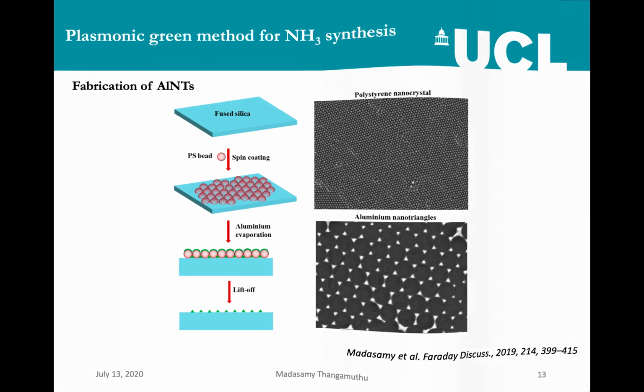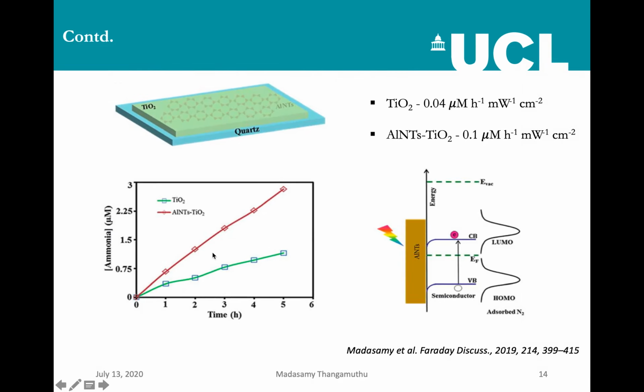In this case, as you can see in this schematic of the electrode, once I fabricated the aluminum nanotriangles, I deposited about 100 nanometers of titanium dioxide semiconductor on top of it. So in my case, who is generating the charge carriers, or where is the electron to reduce the nitrogen molecule coming from? It is from TiO2, obviously, because aluminum can improve the charge carrier generation in TiO2 through plasmonic near field coupling.